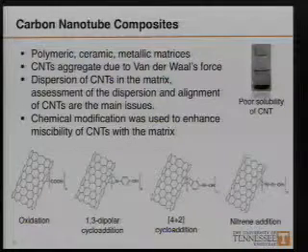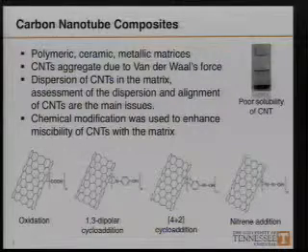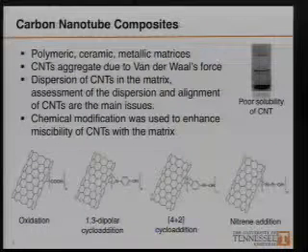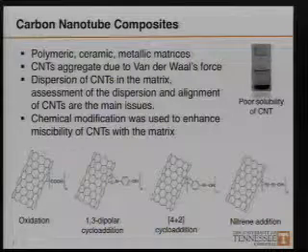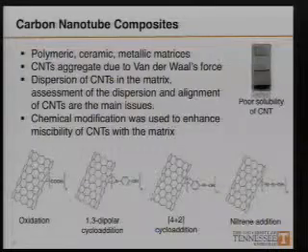One effective route to improve the miscibility of the nanotubes with the matrix is through chemical modifications, including the following routes. Please be noted that the oxidation will create carboxylic acid groups that are versatile for further modifications. However, these harsh conditions could potentially cleave the nanotubes, and it creates some additional defects. Therefore, the other addition-based chemistries are more favorable these days.